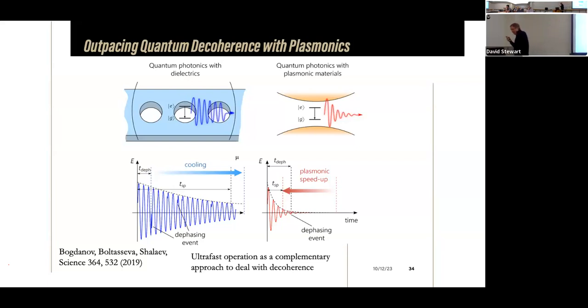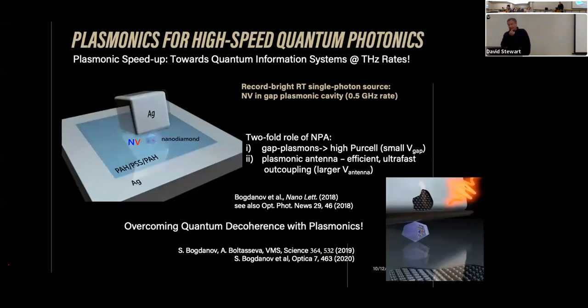And as I pointed out, typical numbers to keep in mind: nanosecond, that's the typical spontaneous emission rate, and picosecond, the typical decoherence time. So we need a Purcell factor around 10,000, which is quite achievable with plasmonic structures. So we started to look at particular antennas which could do this speedup, and this is the quite famous nanopatch antenna. I already mentioned this: a silver single-crystal nanocube sitting on top of an epitaxial silver film.